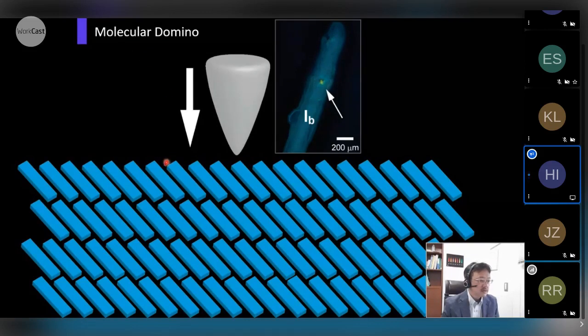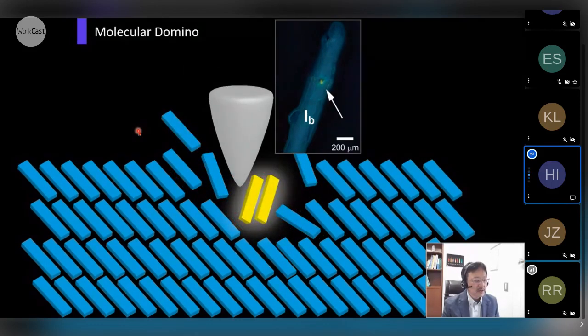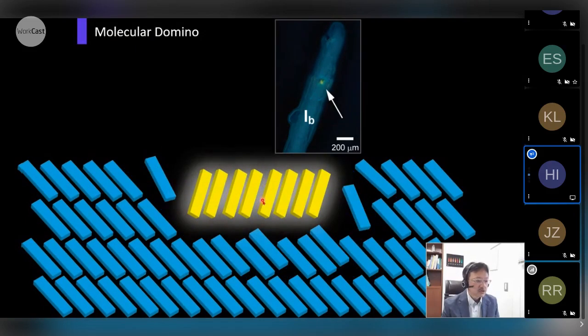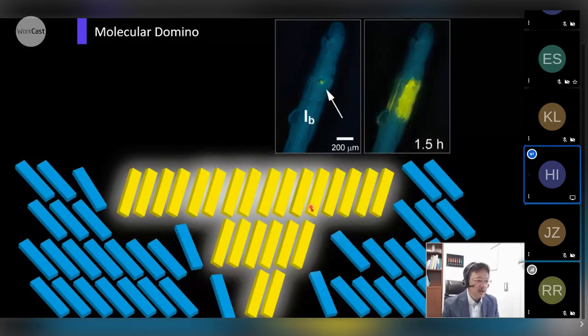At first, the molecule was trapped in the crystal structure in a metastable, kinetically trapped situation. But a small mechanical stress can change this structure to the thermodynamically more stable yellow emissive structure connected through aurophilic interactions. So this part is thermodynamically more stable compared to the blue part. Molecules transferred from the blue part to the yellow to develop the yellow part. This is an explanation of this crystal structure change. It is similar to a seed and growth mechanism. Maybe this is a mechanically induced seed and growth mechanism. So we decided to call this phenomenon a molecular domino.